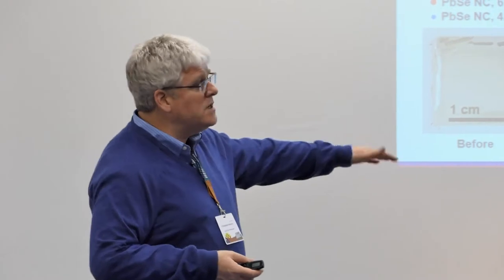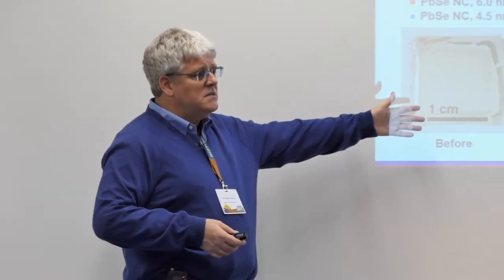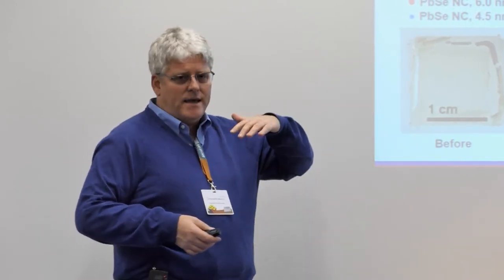So the workaround for this, usually, is that you do it in multiple steps. You deposit the material, you do an exchange, it develops some cracks, you deposit another layer of material, and do the exchange. The fortunate part is that the second layer tends to fill in naturally because of capillary forces and other effects. It goes to the defects, it fills in the gap. So by the time you do about three depositions, you have a very high yield of devices that are electronically active and well-behaved for further characterization.